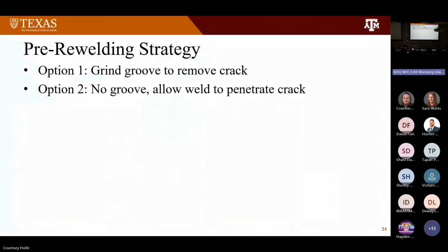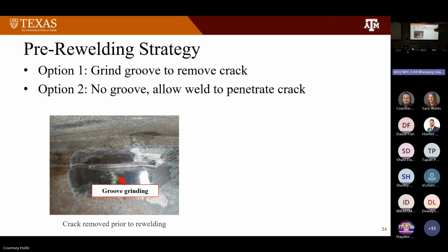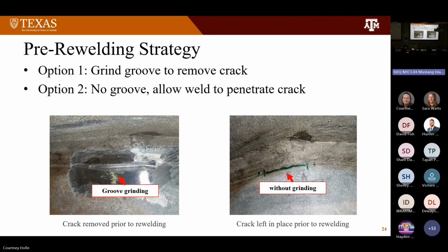Our repair falls into 2 main stages: first, the pre-rewelding stage, and second, the post-rewelding stage. In the pre-rewelding stage, one key decision is whether to grind the groove to remove the existing crack entirely, or just weld over the crack and allow the weld material to penetrate into the crack.